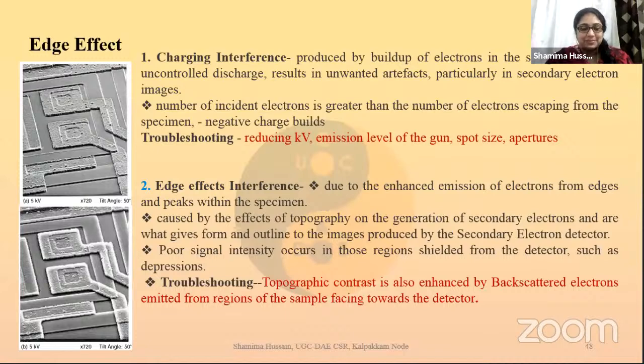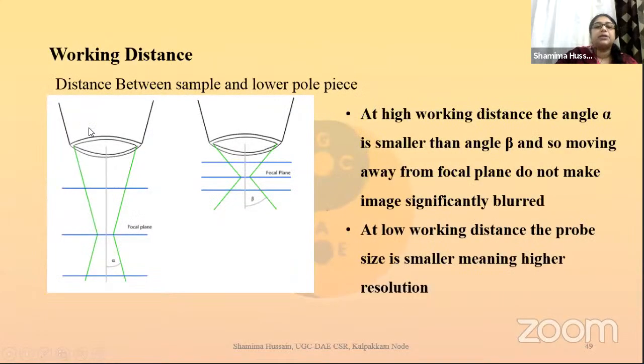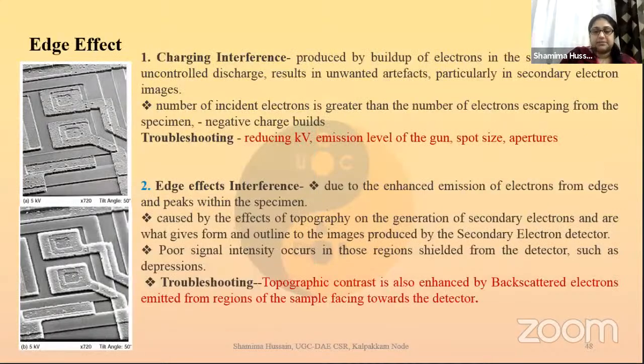And there is something called edge effects also. Edge effect is nothing but the interference for features, related to the depth of focus we mentioned. If the features are slightly higher like this, there will be interaction and scattering at the edges, interference of the electrons coming from the edges, and that is where it appears blurred. So features which are very close to it would not be visible. So what do we do in such cases? A solution would be to reduce the voltage and try to see the images.